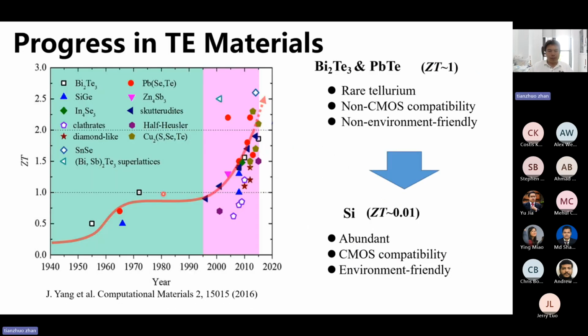For thermoelectric materials, the typical materials used for practical use are bismuth telluride and antimony telluride, and also lead tellurides and their alloys. The ZT value is around 1. But we know there are some limitations for these materials. For example, the element tellurium is rare, and all these materials are not CMOS compatible and also not environmentally friendly. So we need to find materials to solve these problems.